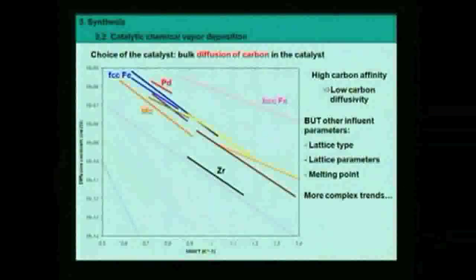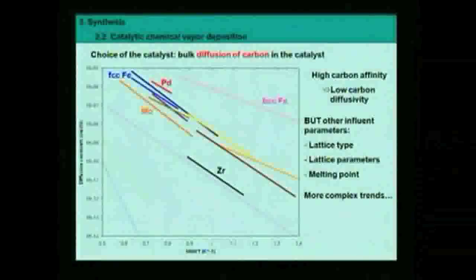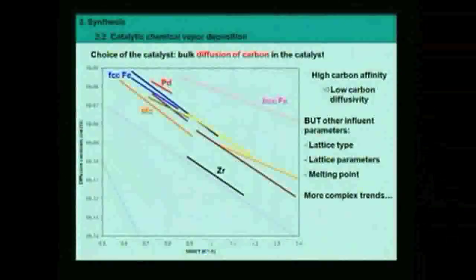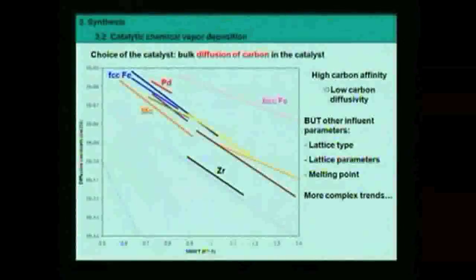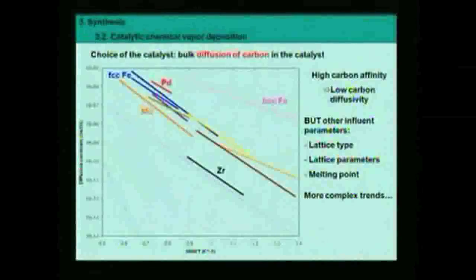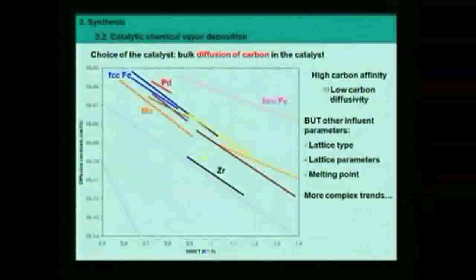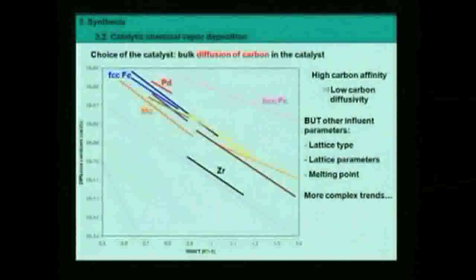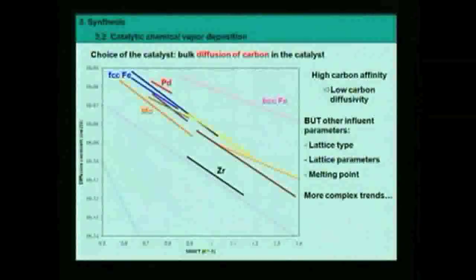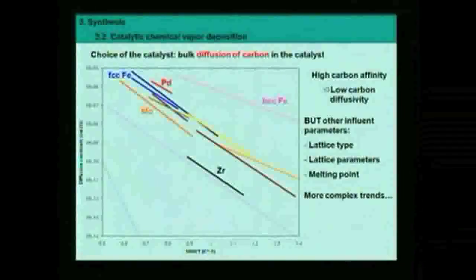So when you diffuse at the surface, you need the atom to go from one position to another. What prevents the atom from going to one position to another? This is the bond between this atom and the surface. You need to break this bond to move from one position to another. And in some cases, you even have to go through a higher energy state, like a barrier, to go to another more stable position. But in any case, the problem is to break, to weaken the interaction with the surface. So you would expect elements with a high carbon affinity, the elements that form very strong bonds with carbon, to prevent diffusion of carbon atoms. And then the diffusion constant of carbon on the surface of those elements or in the bulk of those elements should be very low. Okay?